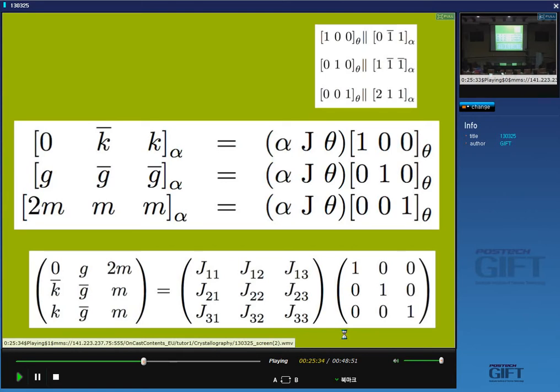I can find the relationship between any direction in cementite and any direction in the ferrite by doing this. I don't need to think about stereograms or anything. This completely defines the relationship between the two crystals, and the determinant of this would give me the ratio of the volumes of the unit cells of cementite and ferrite. Okay? So once you determine your orientation relationship, you can easily obtain the coordinate transformation matrix and do whatever you want